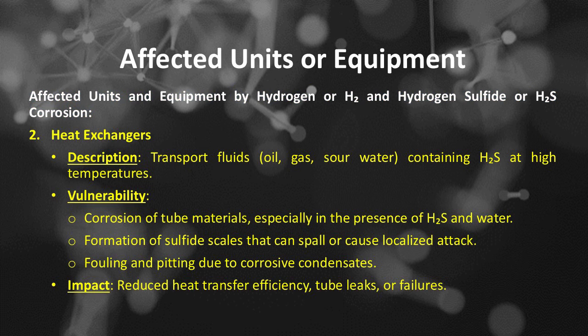The number 2 of the commonly affected units and equipment by high-temperature hydrogen or H2 and hydrogen sulfide or H2S corrosion is heat exchangers. It transports fluids, oil, gas, sour water, containing H2S at high temperatures. The vulnerability of heat exchangers includes corrosion of tube materials, especially in the presence of H2S and water, formation of sulfide scales that can spall or cause localized attack, fouling and pitting due to corrosive condensates. The impact on the heat exchangers: reduced heat transfer efficiency, tube leaks, or failures.